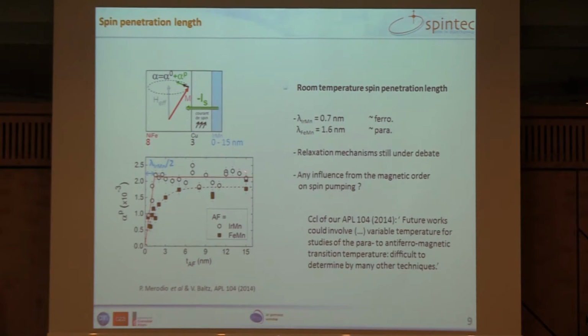So here is a typical experimental result. That's the absorption as a function of the thickness of our antiferromagnetic alloys for 2 alloys, iridium manganese, open circles, and iron manganese, closed squares. So let's have a look at the iridium manganese. We see that the system absorbs the spins up to a certain level where it levels out. So it absorbs as much as it can, and then it levels out.